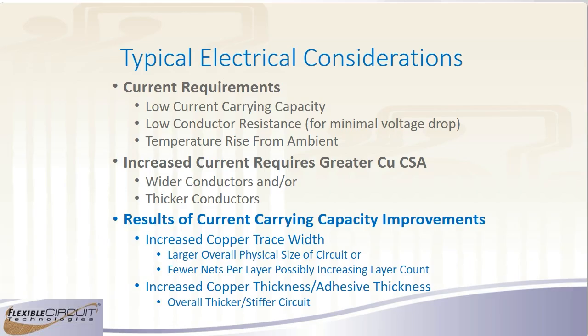If you have an increased copper thickness, if you use a higher weight copper for your traces, you also have to increase the thickness of your adhesive to be able to fill between those conductors. And so that's an additional whammy that you have going. So you end up with an overall thicker and stiffer circuit.